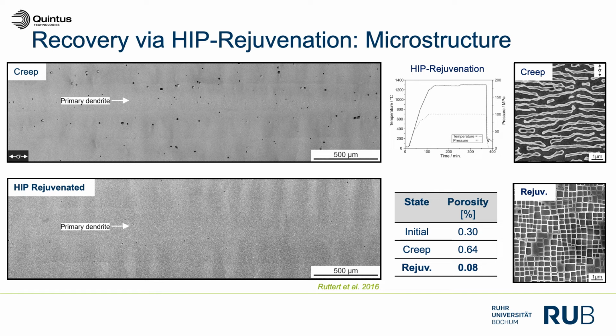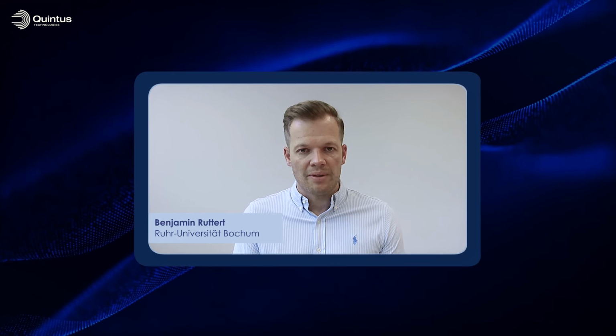So we are able to re-establish the gamma prime microstructure. We can close all the pores that have formed after service. But the most important thing is that we maintain a single crystal after the HIP rejuvenation cycle. It's always a big problem when you introduce deformation into the material after service, after creep, degradation or fatigue. So we have designed a tailored rejuvenation HIP treatment that is able to maintain the single crystal microstructure too.